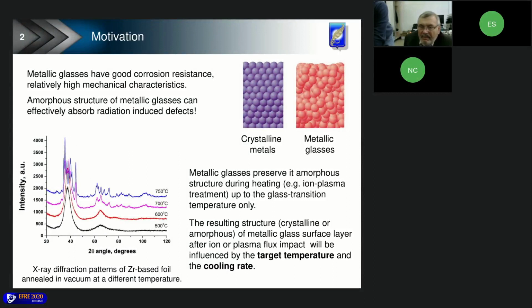A few words about motivation of this work. In general, development of new materials that are capable of working under conditions of high temperature, high mechanical load and radiation is still a challenging task for modern material science. Metallic glasses possess a metastable short-range order structure. This type of material has relatively good corrosion resistance and relatively high mechanical characteristics. But the most important in our case is that amorphous structured metallic glasses can effectively absorb radiation-induced defects, which accelerate material destruction. In particular, radiation stability of metallic glasses under helium radiation is much higher than that of tungsten.